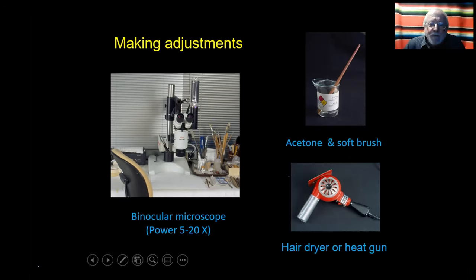If you've made mistakes, you can move it, again, using a little more acetone by softening the join, or you can use a hair dryer or a heat gun. If you're using a heat gun, keep it a fair distance from the glass and also move it around all the time so that you're not heating up one piece or one area of the glass more than another.